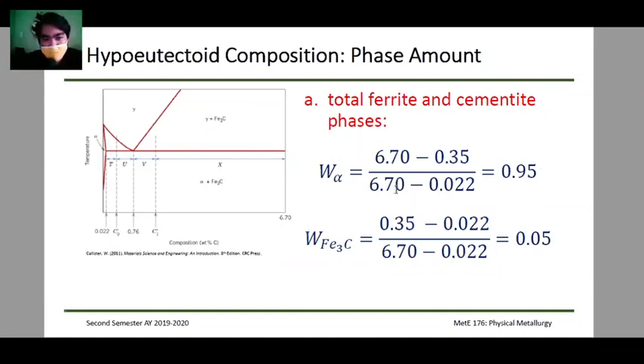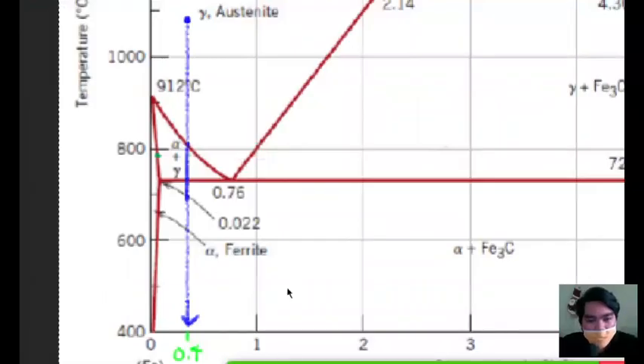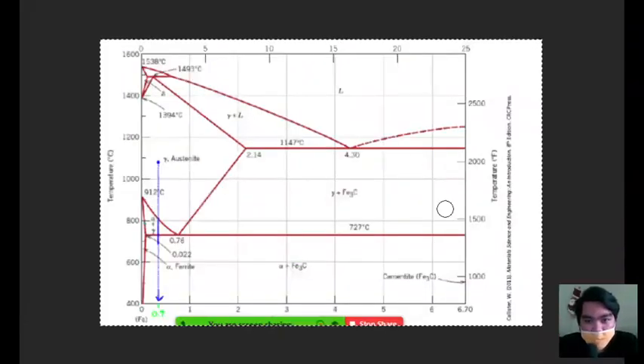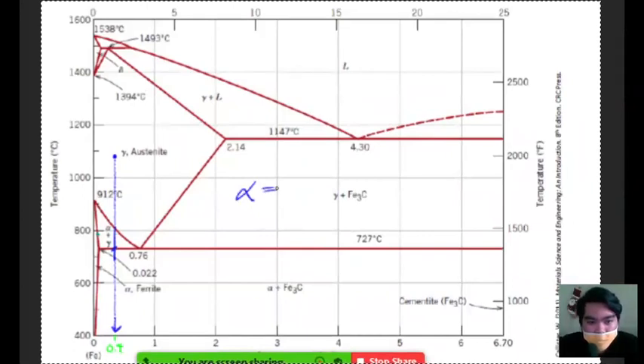Actually, this is not yet the pro-alpha. So this is the total alpha that we have. We are measuring it from the entire tie line, so what we get from here to here is the alpha you produce, a combination of the pro-alpha plus the alpha in the eutectoid composition, or eutectoid mixture, which is let's just say the pearlite. So this is the pro phase plus the pearlite phase, the total when we take it from here to here.